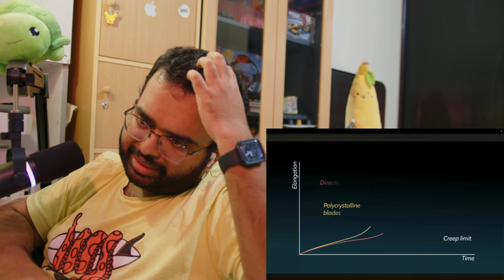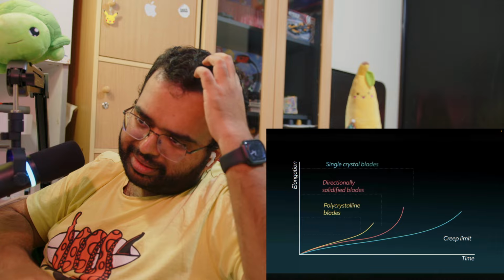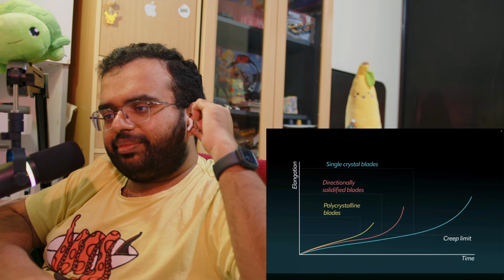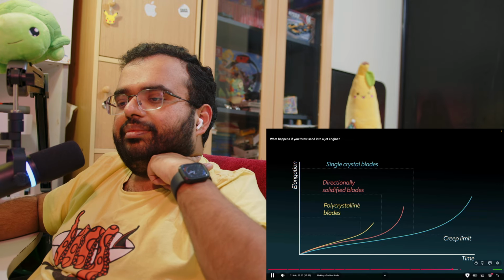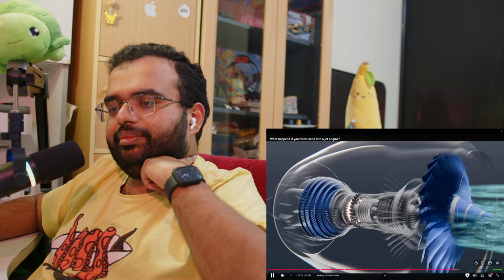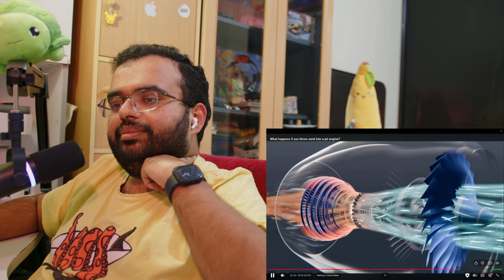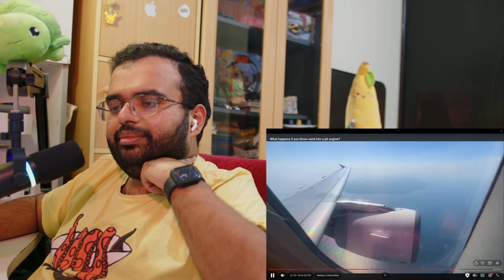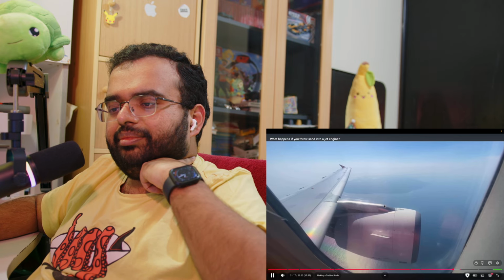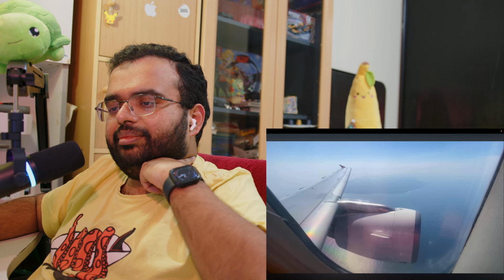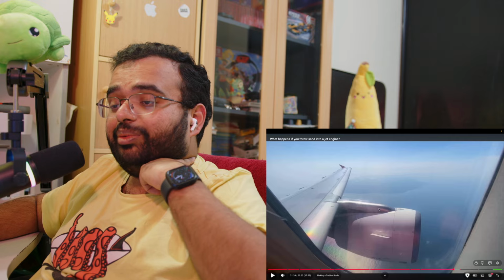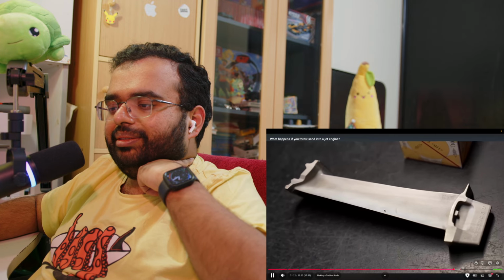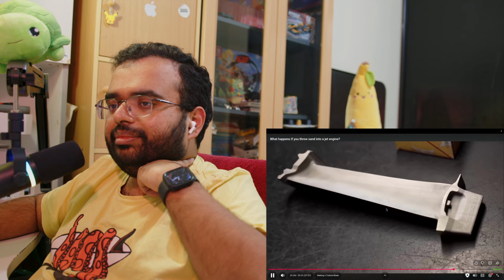This completely transformed what jet engines can do. Single crystal blades can withstand stresses and temperatures that would destroy ordinary alloys. They last up to 9 times longer against creep and thermal fatigue, and are more than 3 times more resistant to corrosion than blades made from multiple grains. That's why modern jet engines can now run for 25,000 hours between major overhauls. Which is insane to even think about. Something that would have been unthinkable before single crystal blades.